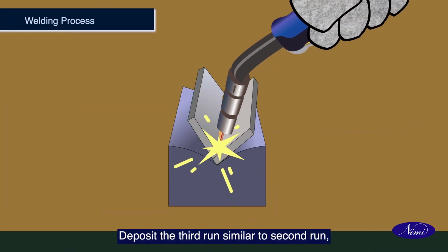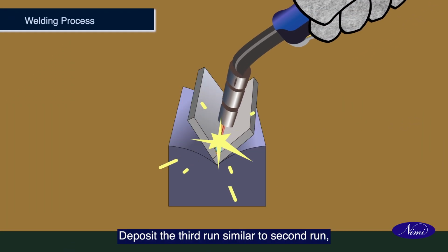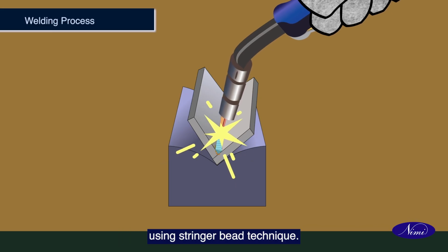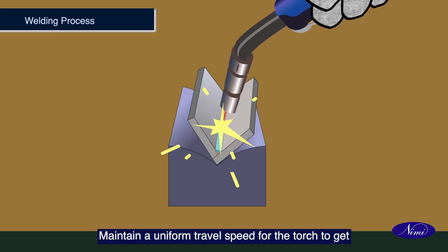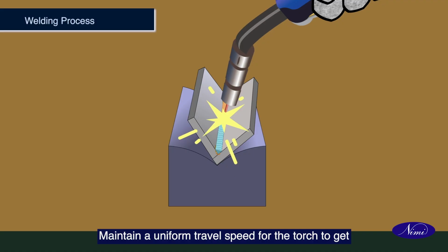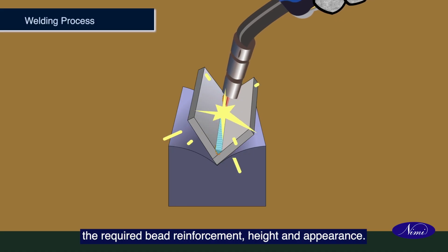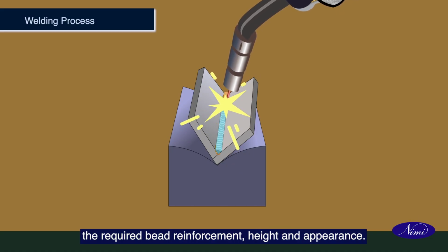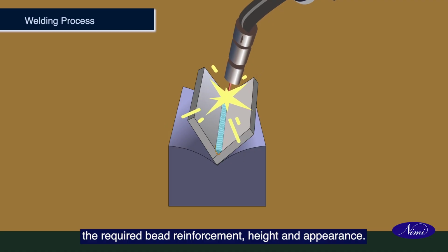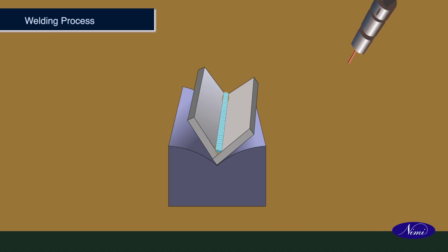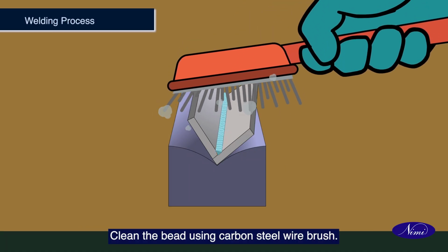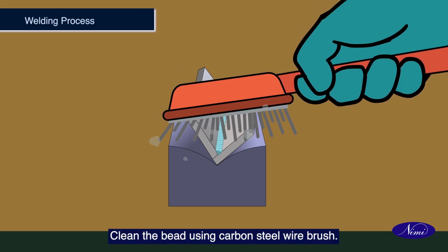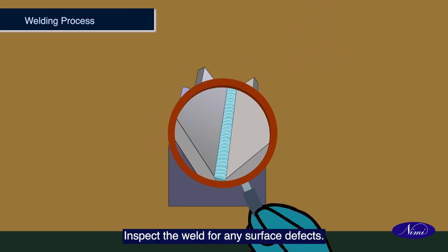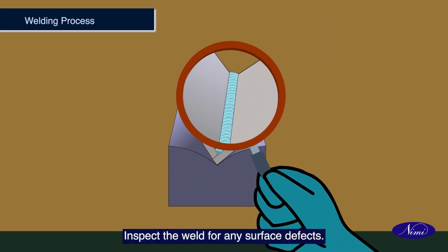Deposit the third run similar to second run using stringer bead technique. Maintain a uniform travel speed for the torch to get the required bead reinforcement, height and appearance. Clean the bead using carbon steel wire brush. Inspect the weld for any surface defects.